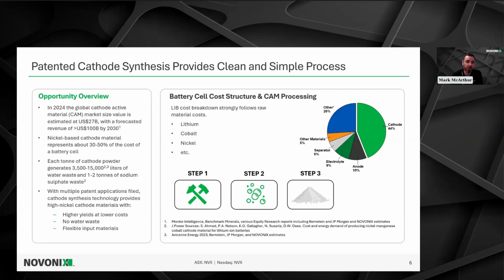Depending on the market reports you're reviewing, in 2024, the global cathode active material market was estimated to be roughly $27 billion, and that was forecasted to eclipse $100 billion by the end of the decade. And there are two main cathode active materials which are utilized in lithium-ion battery technologies today. One is iron-based LFP, or lithium iron phosphate type, and the other is nickel-based cathode materials, or NMC, NCA type, where you have nickel, manganese, cobalt, or nickel, cobalt, aluminum.